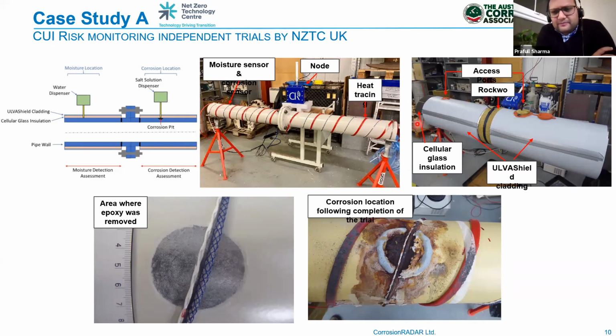And one last question, what is the theory of this technique based on: insulation layer conductivity change or pipe wall thickness difference, from one of our guests? Yes, so the technique is neither of that. In fact, it does not interact with the pipe or the asset surface at all. It does not measure anything on the pipe or the asset surface. It does not measure the thickness reductions or corrosion on the surface. All it does is, in case of a moisture sensor, it is detecting moisture on itself. Say when the condensed water touches the moisture sensor, a signal comes that, hey, this is the location, because of time of flight.